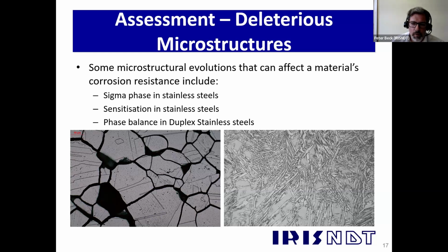So you would put a grid pattern across that and do a count basically to work out the percentage of austenite and ferrite, and that has quite a key impact on your corrosion resistance, the amount of austenite to give you that corrosion resistance.